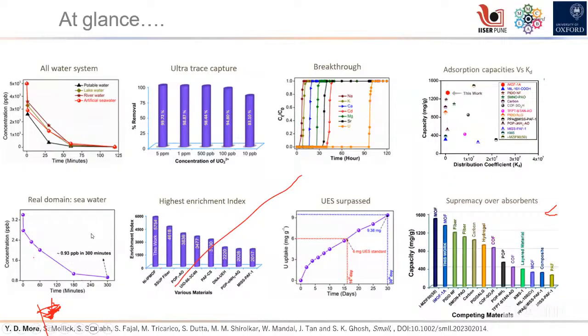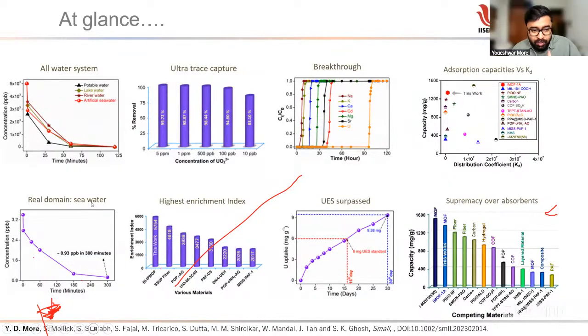Then we did a real domain in seawater. So we were able to go down. Now we analyzed the real seawater, which is 3.3 ppb. Then we did this extraction, and the leftover was 0.93 parts per billion. What does that mean? Out of 3.3 ppb, only 0.93 parts per billion is left, and the remaining amount is taken by the MOF in 300 minutes. We are not able to do it in 120 minutes. We are able to do it in 300 minutes, that is 5 hours. And then we did a breakthrough.